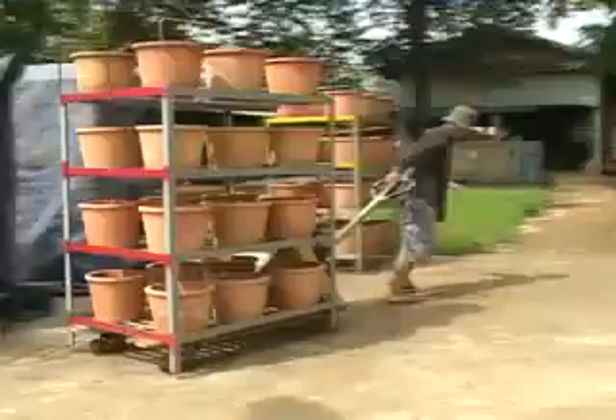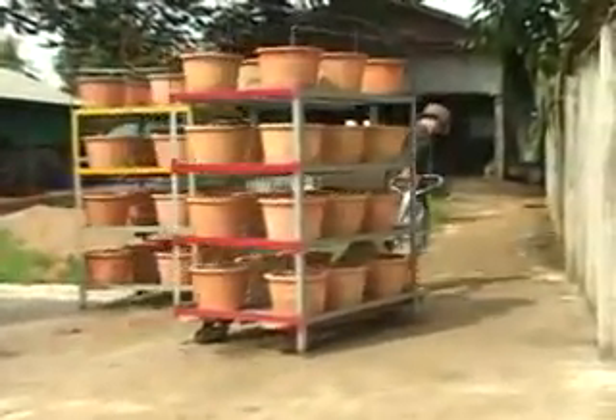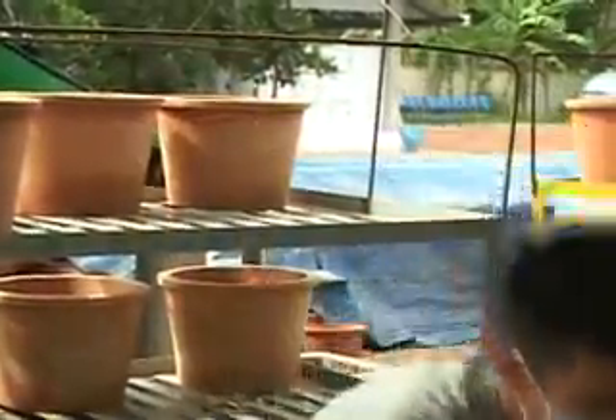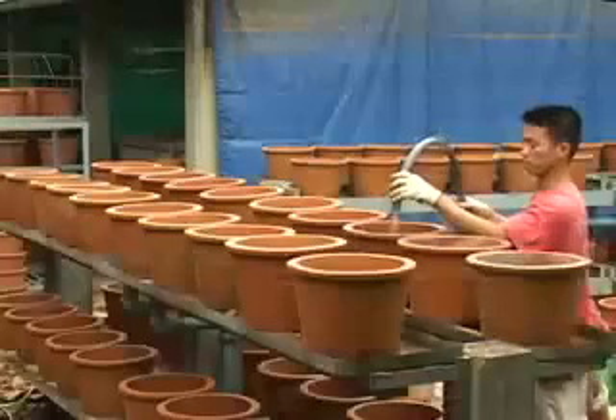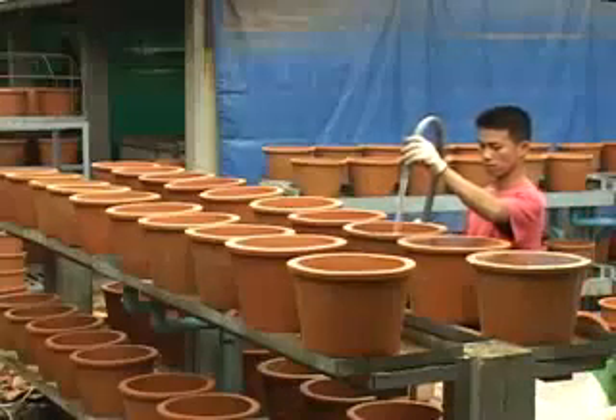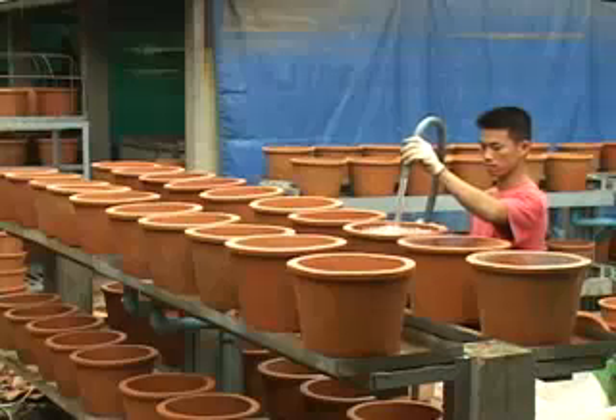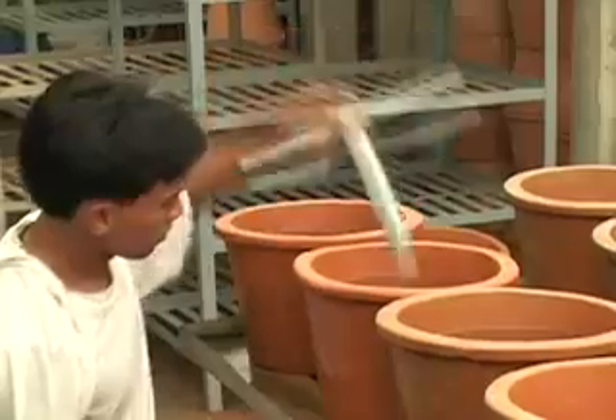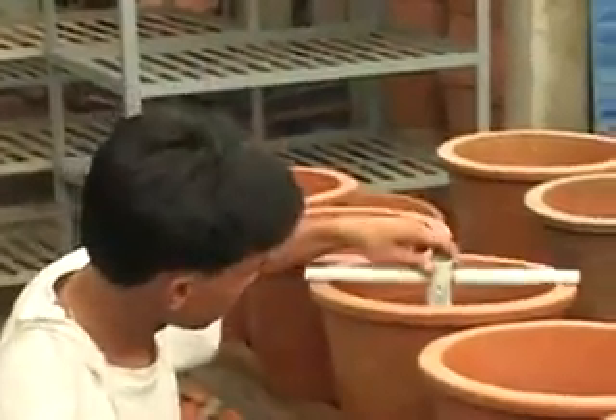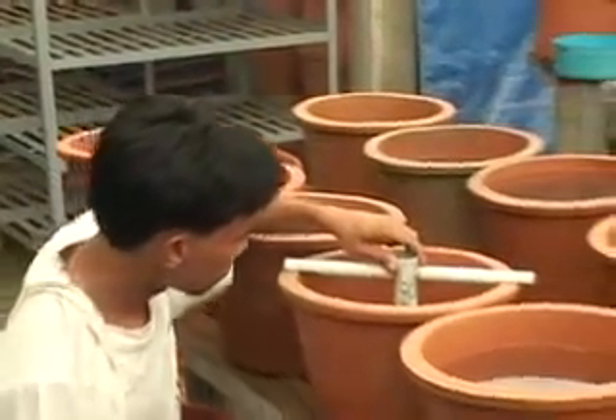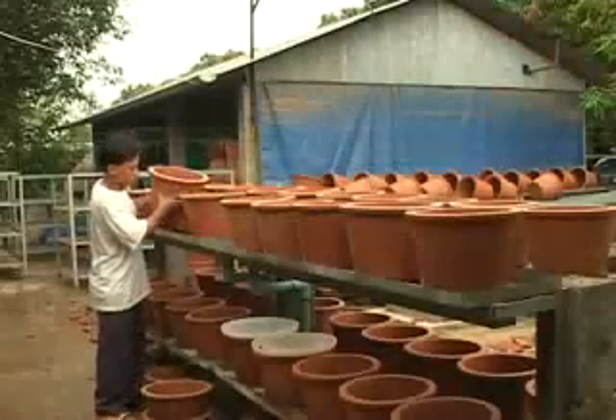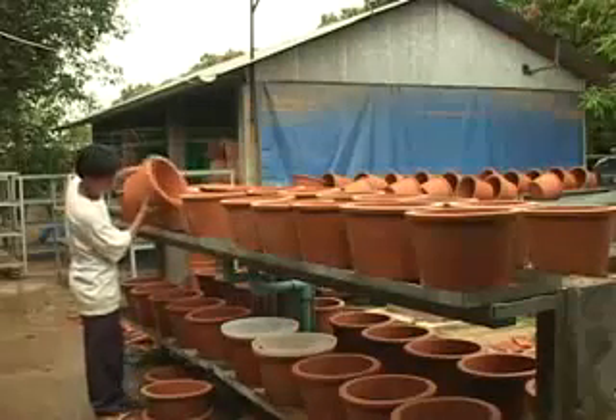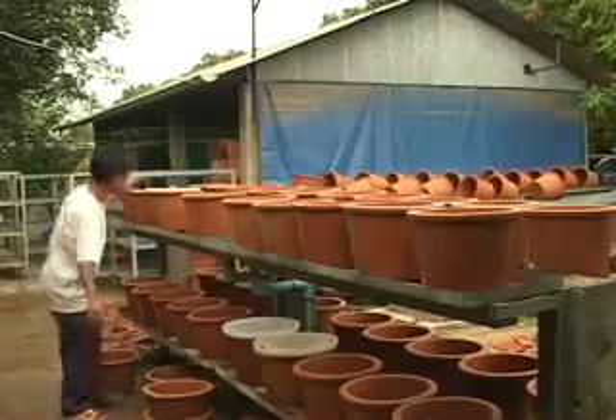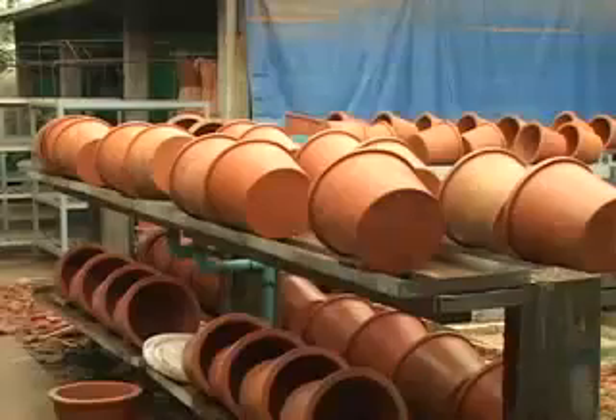The filters are then rolled up to a soak tank. Filters are soaked in the tank for a minimum of 3 hours. Then they're placed on the flow testing racks. The filters are filled to the brim and a timer is started. At the end of 1 hour, a special measuring device is used to determine the flow rate. If filters have a flow rate outside of tolerance, they are immediately removed from the process. High quality control is essential to the future of the filters. Filters that pass the flow rate test are dried and then taken over to an area to be treated with a silver solution.